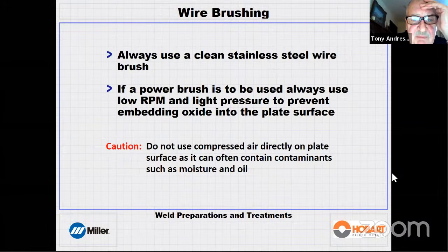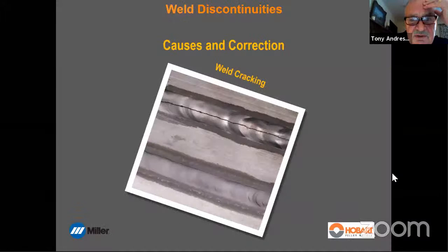All right. The other thing, if you're going to power brush, be careful, don't overdo it. Use light pressure, low revs per minute, because you can actually churn that oxide and embed it into the surface of the material. So be careful. Be careful with compressed air also, because it can cause a lot of contamination. It's not usually very clean.